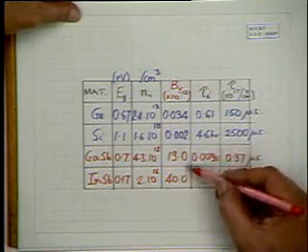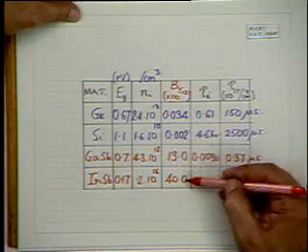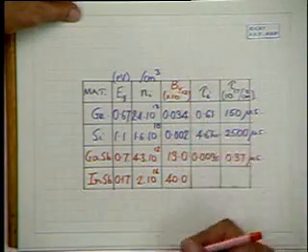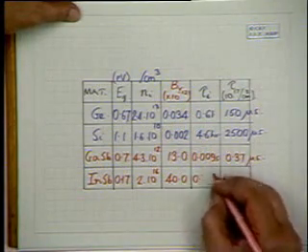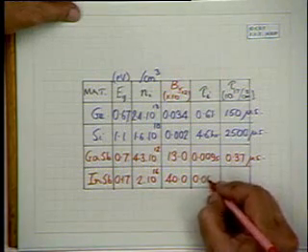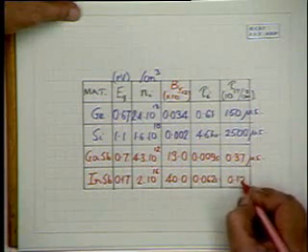So you see that there is about 4 orders of magnitude difference between a material like indium antimonide and germanium. Here, the value of tau I is about 0.026 seconds, and tau is about 0.12 microseconds.